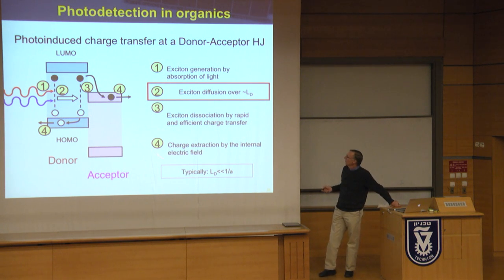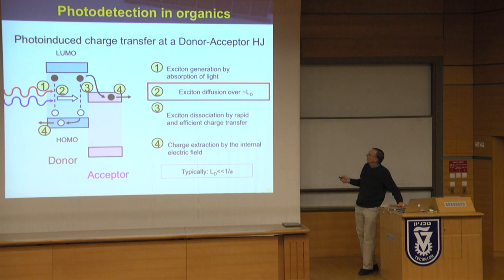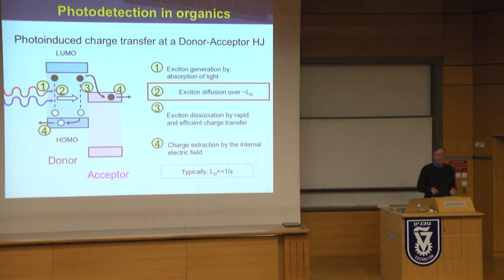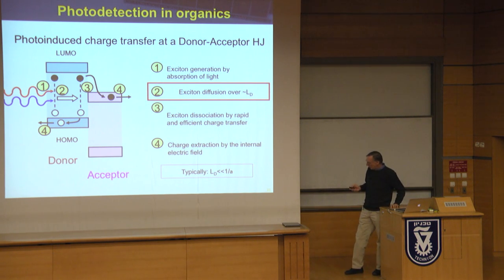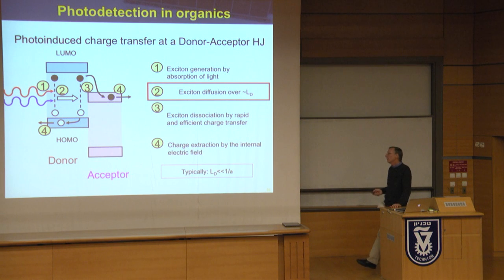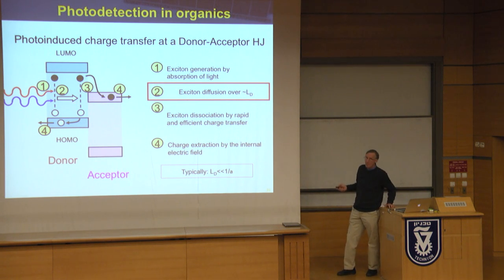There are 4 different steps to it, and the efficiency is the product of all those steps. So if any step is less than 1, it's going to hurt you. And people have been working a long time on maximizing these efficiencies. The biggest problem is that although these are highly absorptive materials, it takes a long distance on the order of 1,000 angstroms for a photon to be absorbed.